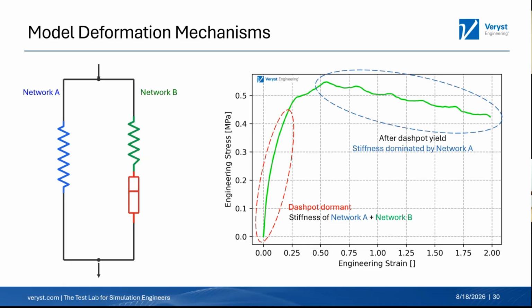But what is this model? How does this model behave? I showed you all those parameters. I showed you that schematic, but what does each one mean? So I've taken just one of our curves there, that green curve at the lower rate. That's a tension test, and I've tried to show what happens in each part of it. In the first, say, 20% strain, where we've got a moderately straight line, the dash pot is not activated. By activated, I mean we're not getting a lot of strain or displacement in that dash pot. So really, we just have a model that has the stiffness of network A and network B.